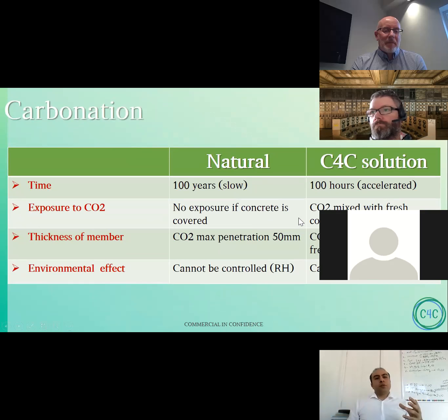Next page, please. So just having a comparison between carbonation happening naturally and our technology. Carbonation naturally happens over a period of 100 years, and we are accelerating that to 100 hours. So in a normal situation, a concrete member should be exposed to CO2 from the atmosphere for 100 years. However, normally we cover our concrete member with render, facade, or a lot of elements, so we hinder the carbonation. However, in our technology, we mix that uniformly with CO2. So CO2 is available at any depth of our concrete.